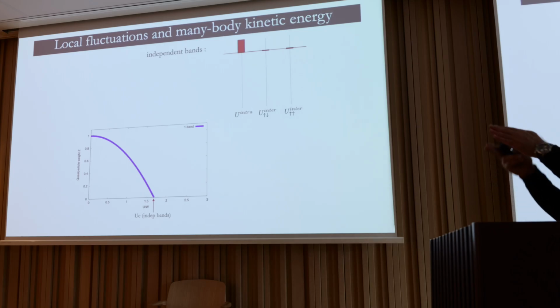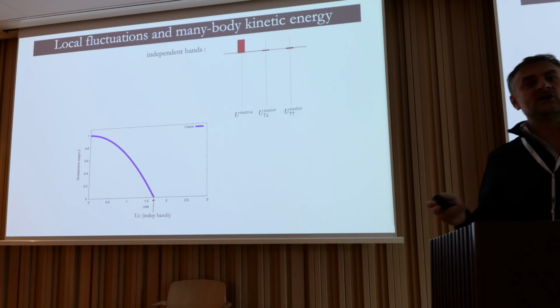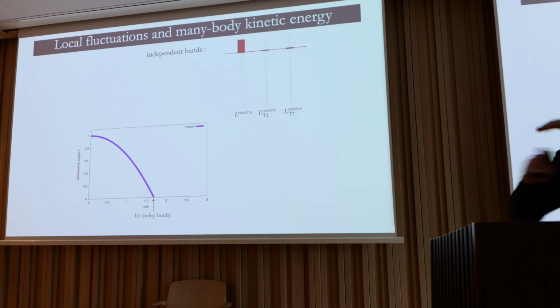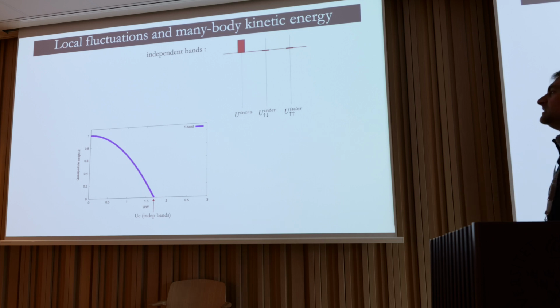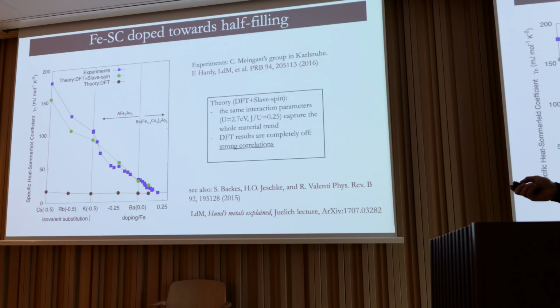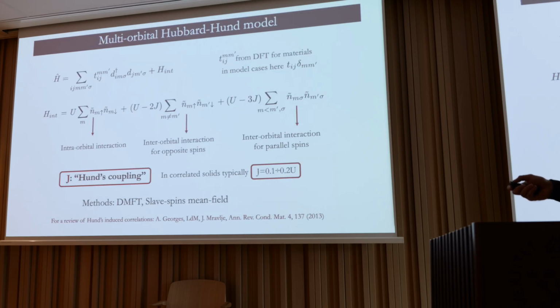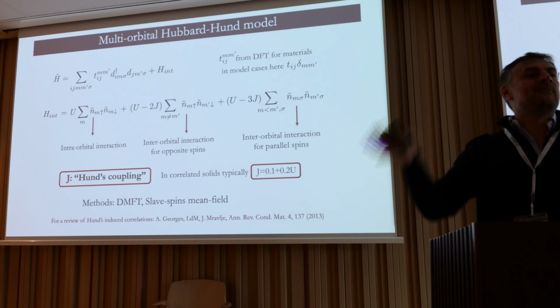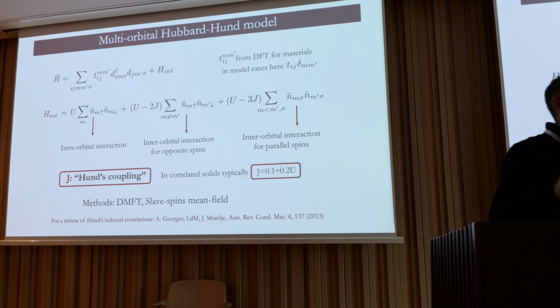I will be talking for now about 10 minutes about models which have the same interaction but simplified bands, and then we will go back to the iron-based superconductor band structure in detail. Instead of doing all the complicated t ij m m prime, I can put nearest neighbor hoppings between the same orbitals, so I will have 5 bands with featureless density of states.